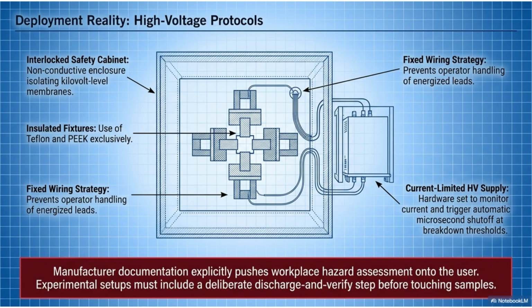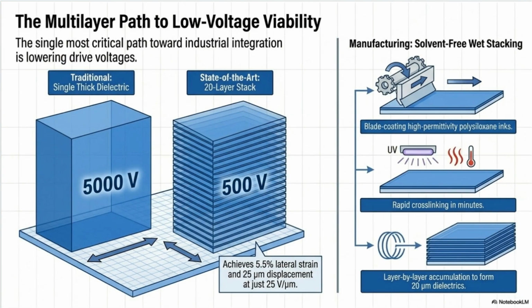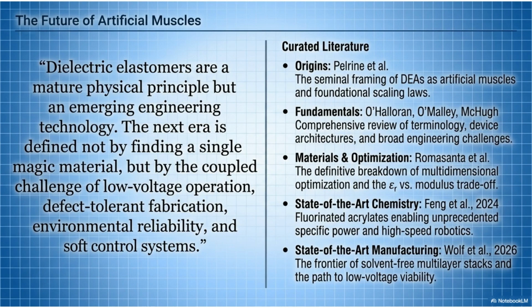These include interlocked safety cabinets, insulated fixtures, fixed wiring to prevent handling energized leads, and current-limited HV supplies with automatic shutoff at breakdown thresholds. To achieve low-voltage viability and industrial integration, a multi-layer approach is critical. A 20-layer stack, compared to a single thick dielectric, achieves high lateral strain and displacement at 500 volts instead of 5,000 volts. The future of artificial muscles is defined by a coupled challenge: low-voltage operation, defect-tolerant fabrication, environmental reliability, and soft control systems. Dielectric elastomers are transitioning from a physical principle to an emerging engineering technology.